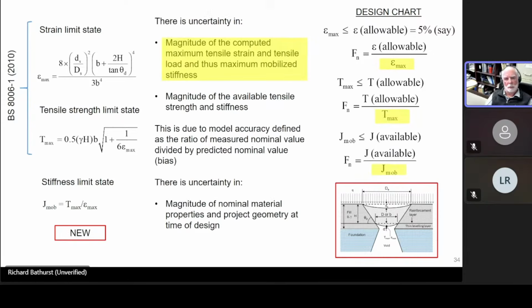And this is a challenging question, because when you look at each one of these limit state nominal factor equations that you see on the right-hand side, there is uncertainty. There's uncertainty in the magnitude of the computed tensile strain using your formula here for the British standard, or an equivalent formula for any one of the other methods that I introduced before. There's uncertainty in the magnitude of this computed maximum load. And because there's uncertainty in the strain and the load, there must be uncertainty in the mobilized stiffness of the reinforcement.